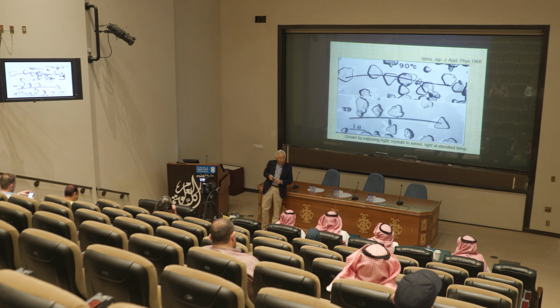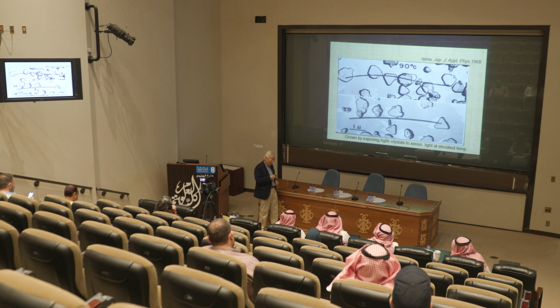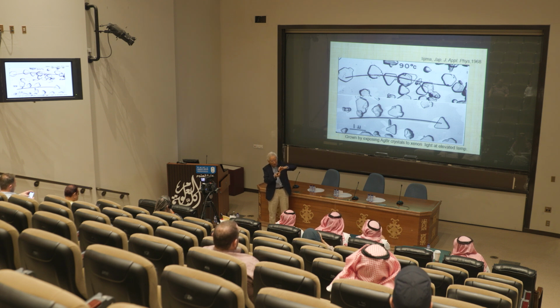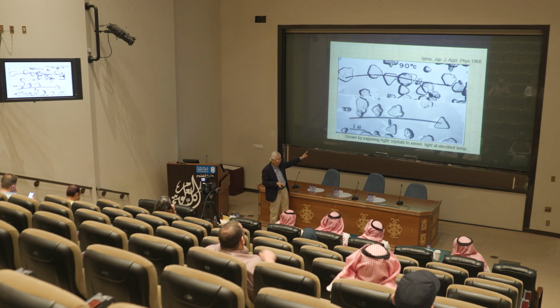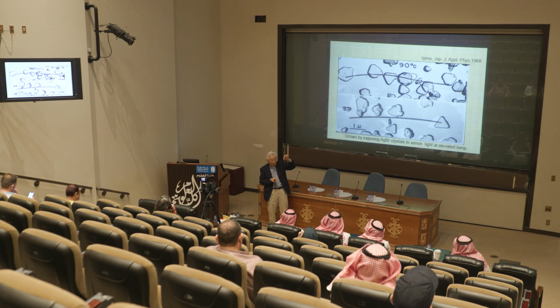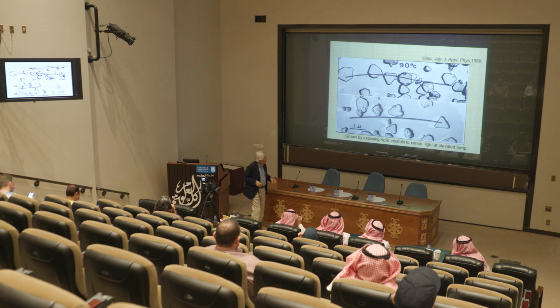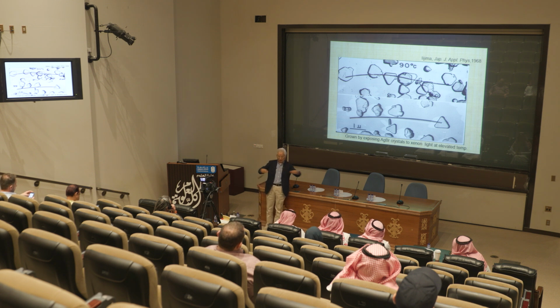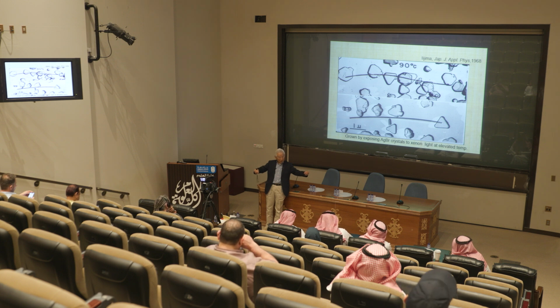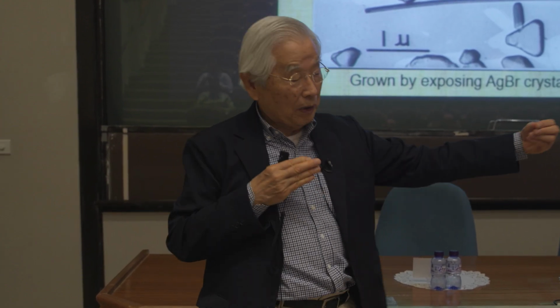Then yes, this is another of my experiences. When I was a master student, I had been working on this filament, and part of my doctoral thesis is about this. This is silver bromide. Somehow, silver bromide, the filament growing. This is not a single crystal, but this is very unusual. If you grow any material, always you have sort of a bulk block. It's not going like that, and it's anisotropic, the growth. So I checked what happened in the filament, and I found the defect, which is a twin defect along the filament axis. So that makes the anisotropic crystal growth.